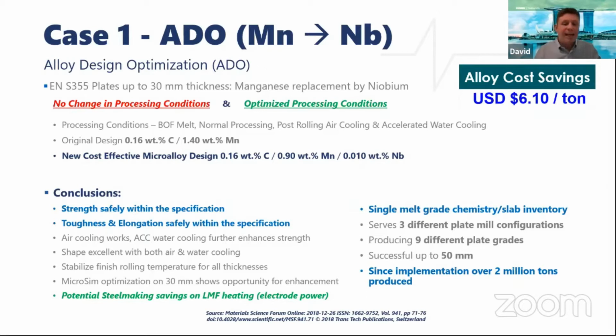It covered up to 9 different plate grades related to the same strength range and up to 50 millimeters thickness, all using one chemical composition. That increased considerably the yield of the continuous casting because you have no more transition slabs when you change the chemical composition. And that gave the company a very important savings in slab inventory cost. Since implementation, this concept has already produced more than 2 million tons, and it's fully commercial.